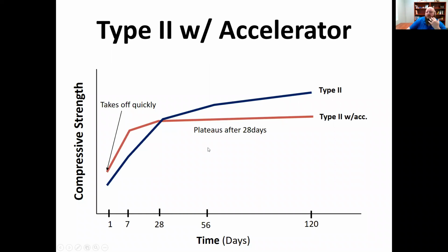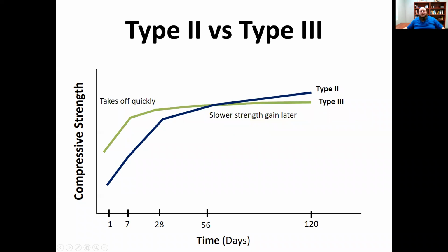Type 2 with an accelerator. This is going to speed up the reaction to begin with at an early age, and then maybe at 7 or 28, it's going to start plateauing. So just kind of recognize that type 1 or type 2 versus type 3. Typically, a type 3 is either a type 1 or a type 2, and it's ground down finer. So you're going to have more surface area with a type 3 cement, so you're going to be able to get a quicker takeoff. But again, like I said before, at 28 days or 56, things with a type 3 start slowing down. So just be aware.